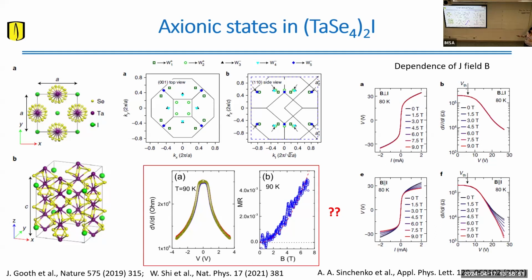So precisely the chiral anomaly. Meaning you will have a contribution to your conductance and your current through an E.B term. If you increase the magnetic field, this E.B term will be stronger. So you would expect a larger contribution to the nonlinear conductance in this regime here. And because it is in the regime in which your conductance is nonlinear, you could claim that this is due to a displaced charge density wave, meaning a phason that picks up this chiral anomaly term.